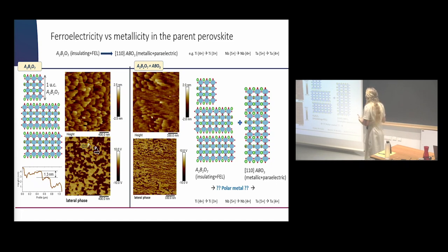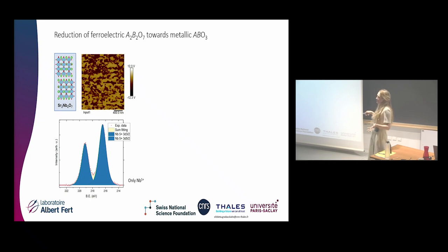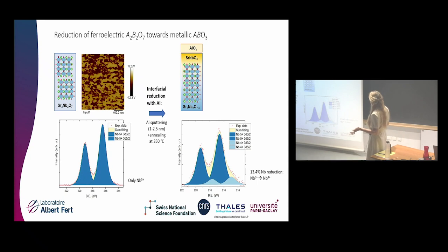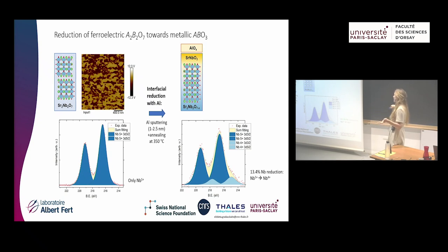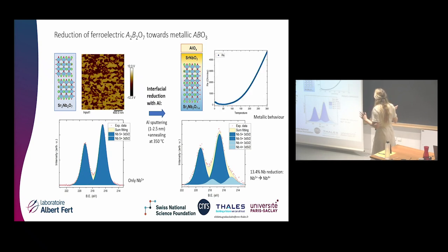So the way we want to tackle this is to start with the ferroelectric insulating phase. So we do some XPS, we see that, okay, we have niobium 5+, so only the insulating variant. And then what we do, it's a bit what you heard in the morning already. We deposit some aluminum on top and anneal in hopes that aluminum will collect all the oxygens, form aluminum oxide, and then reduce the film below. And then hopefully we should have something at the interface, which is the conducting parent phase, or at least reduced layered phase. And then in XPS, we can see that, okay, indeed, we have the Nb4+ peaks that appear after we put the aluminum capping. And it looks like we also have some metallic behavior, but this is very new data, and we need to look into it more. But it seems to be that the general idea of maybe being able to have this topotactic-like reaction, starting from something ferroelectric and finishing with something that's conducting, is also possible, clearly with a polar metal in between.